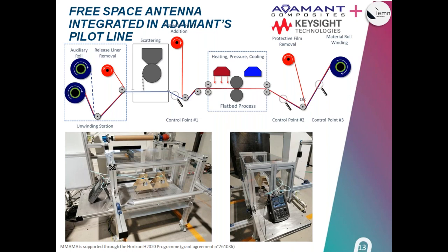Then there is the compaction process. We use a specific machine for that, where we use heat and pressure to compact the powder with the substrate prepreg. And then at the end, we have a station where we can remove the protective film that we insert for the compaction process, or we can leave it and wind it at the end as the final product. What you can see as magnifying glasses are three positions that we have identified in the MMAMA project as positions where we could integrate the free space antenna system.